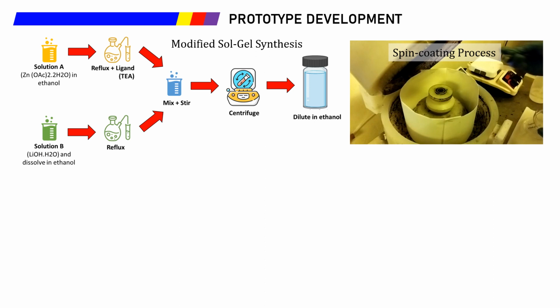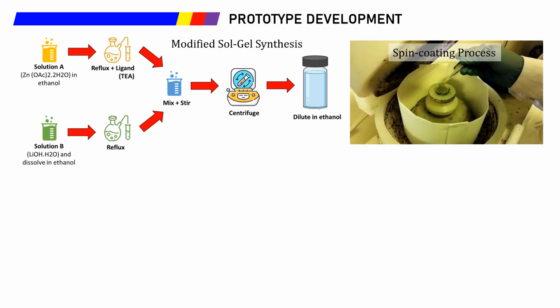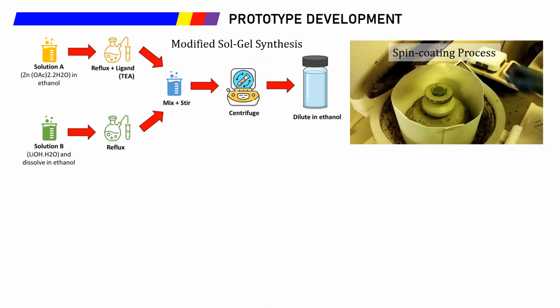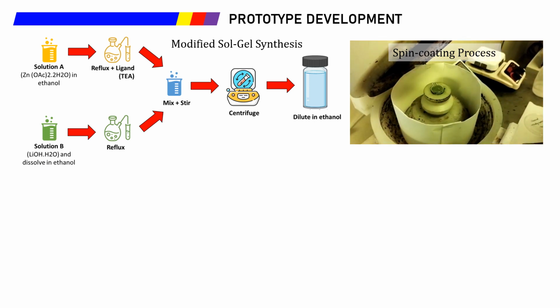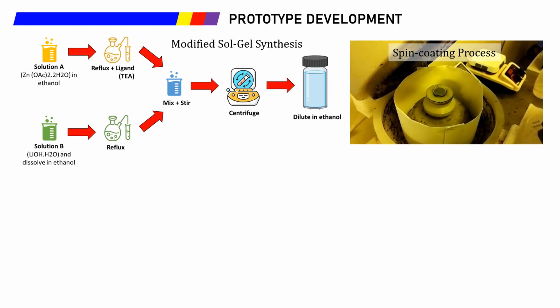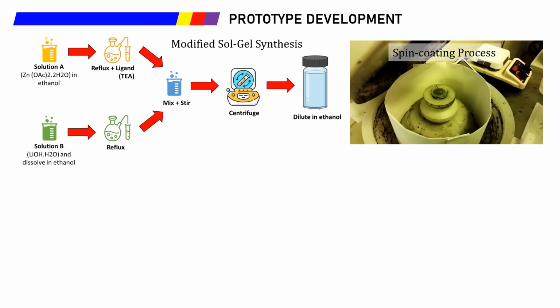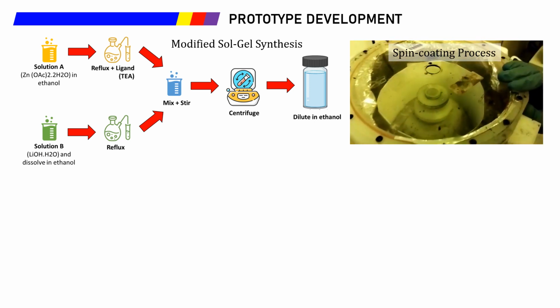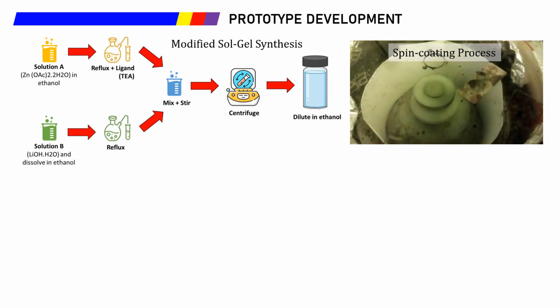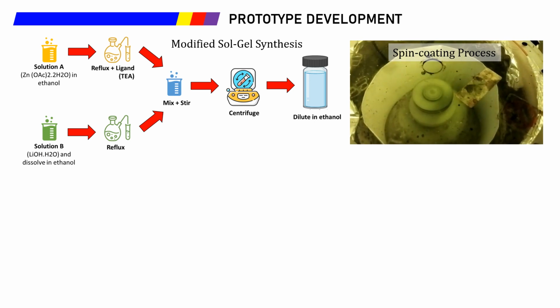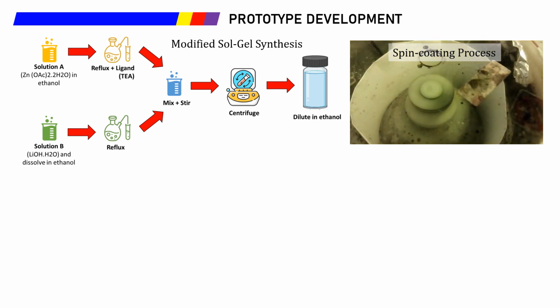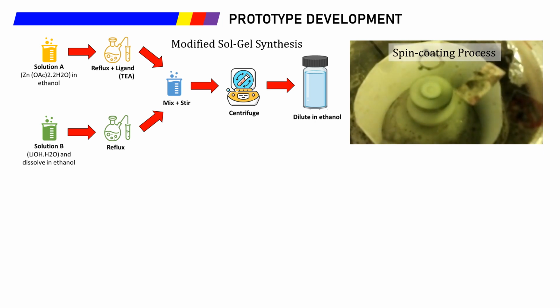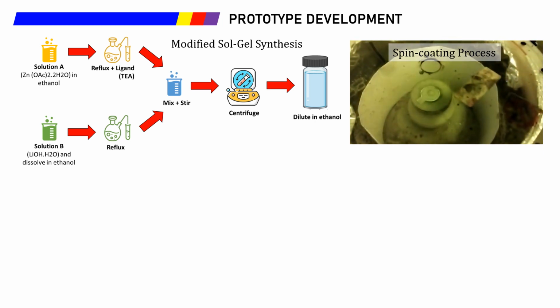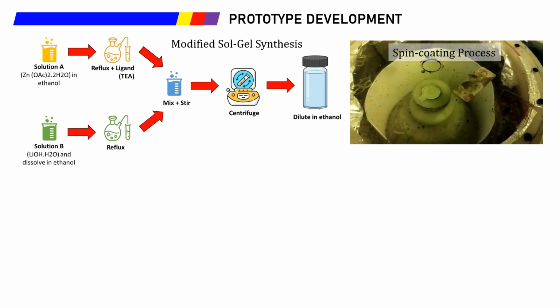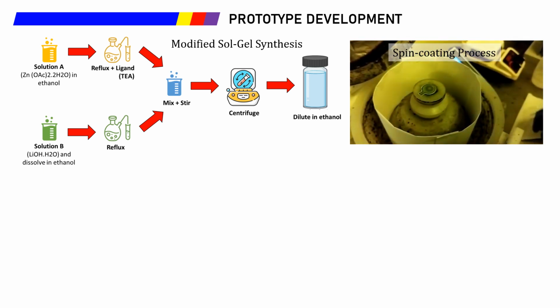The zinc oxide quantum dots were synthesized by using the modified sol-gel method. Two precursors were prepared before synthesis, which were zinc and lithium hydroxide precursors. The lithium hydroxide solution was added to the zinc ion precursor solution and the mixture was vigorously stirred for 10 minutes to form a homogeneous solution. Finally, white solid zinc oxide quantum dots were recovered by centrifuging the solution with added excess acetone to induce precipitation. The obtained white solid zinc oxide quantum dots were then redispersed in ethanol and spin-coated on the interdigitated sensor electrode.